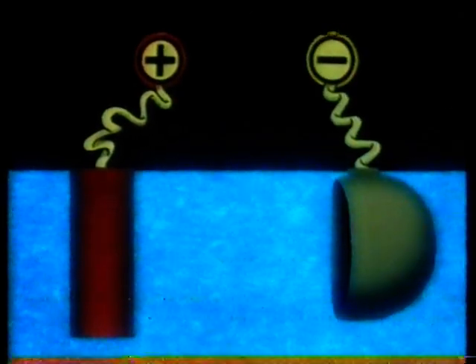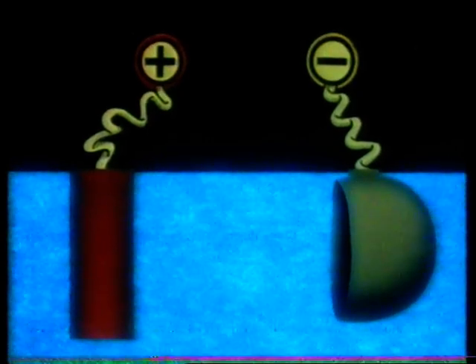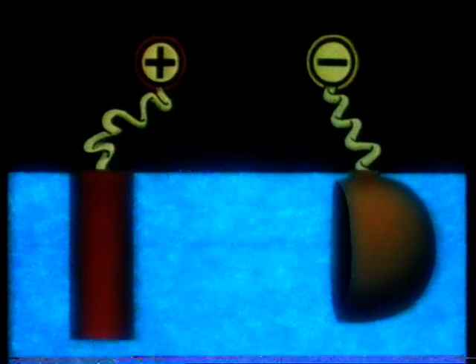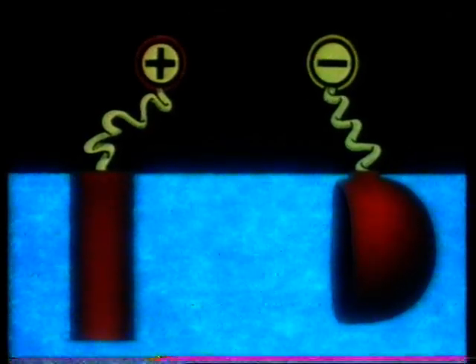But this equipment is coating zinc with other metals, copper, nickel, and for a shiny surface, chromium. The coatings of metal are joined by electroplating. Copper is the first layer on the bare zinc. Large copper rods form the anode of the cell. Copper sulfate is the conducting electrolyte, and the zinc is the cathode. Gradually, copper ions move from the electrolyte and form a thin layer of copper on the zinc.